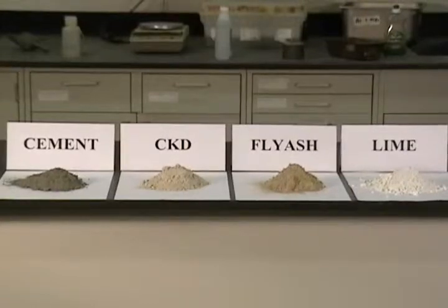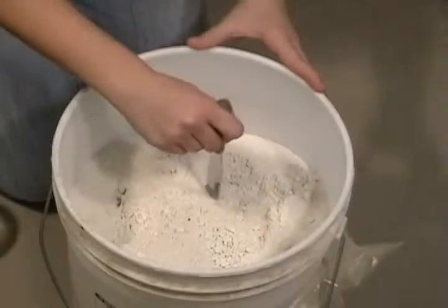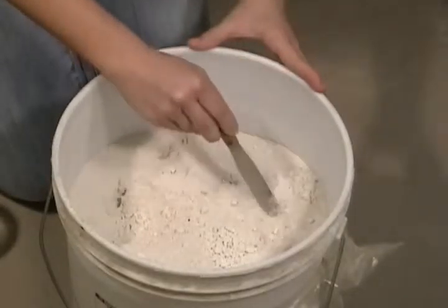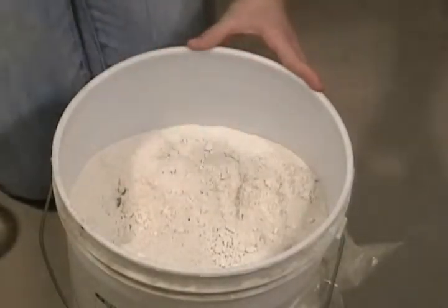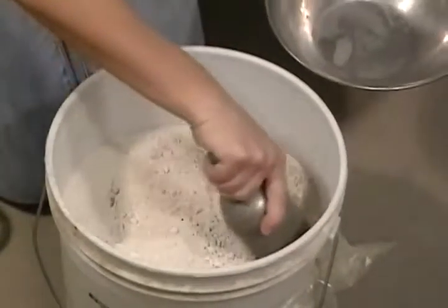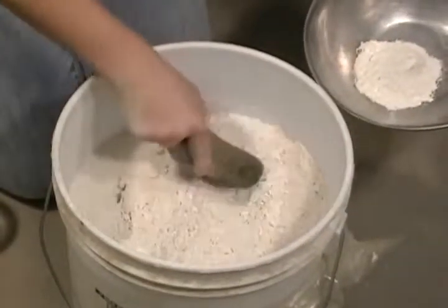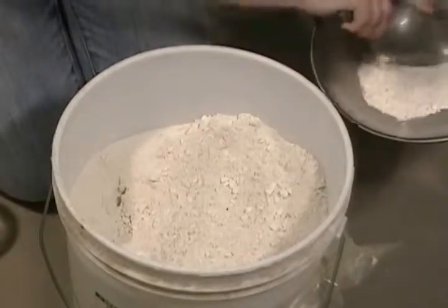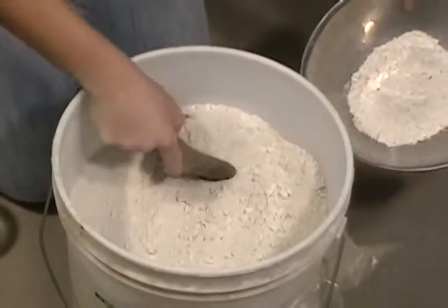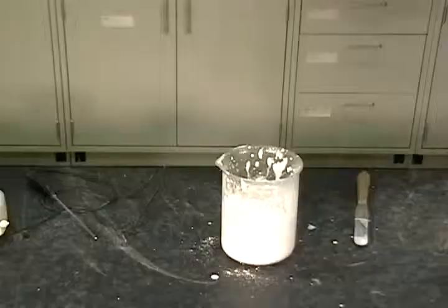Lime, cement, and fly ash are shipped as dry materials with a powdery to pebbly texture. All products must be fresh, as exposure to moisture or air will, over time, render the material ineffective. Containers of material used for lab testing should be kept closed when not in use, and fresh material obtained on a regular basis. Material that has reacted with the air may form a surface crust. This material should never be used for test samples. For testing conducted as a part of design or research, it is good policy to confirm the freshness of supplies or to replace supplies on a monthly basis.